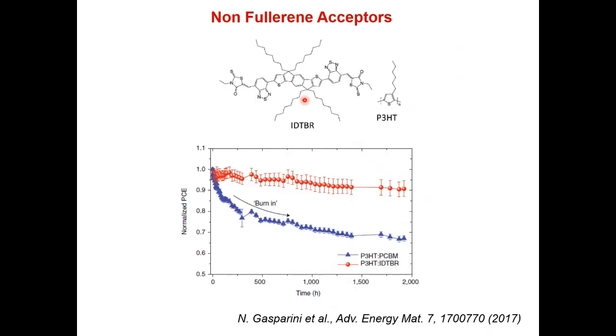Another main advantage of the non-fullerene acceptors, this new generation, is the stability, because you want a stable device, of course, when you are going to install it. You see that with PCBM, the efficiency drops very quickly, which is bad for the device. With those new materials, the chemical stability is also very good, and you get an almost constant efficiency after 2000 hours, which is very good for a product.